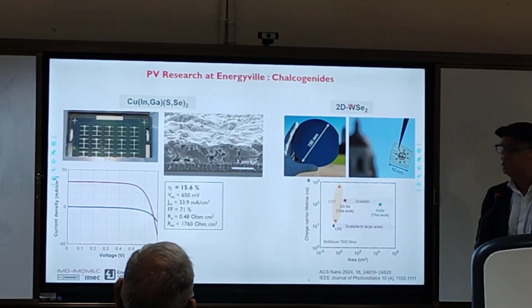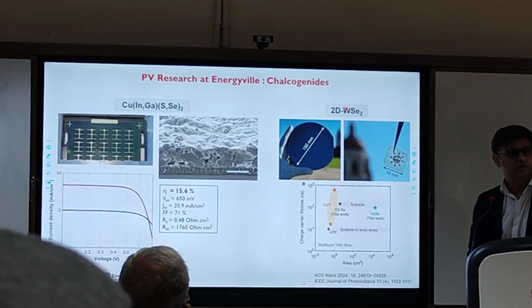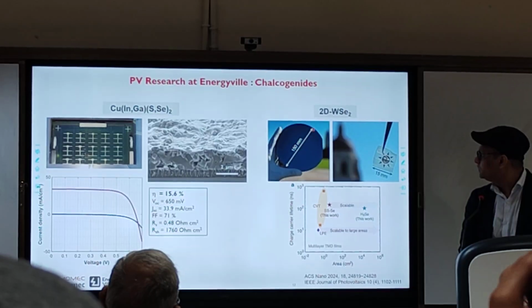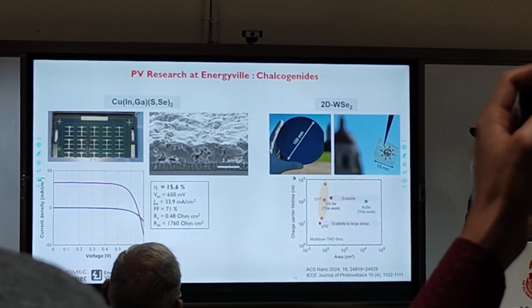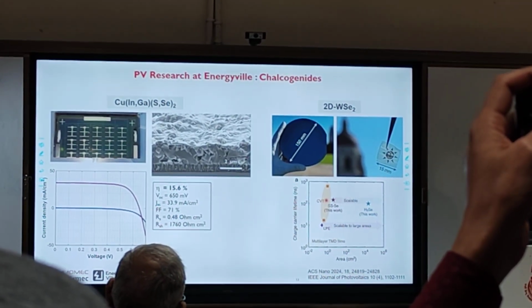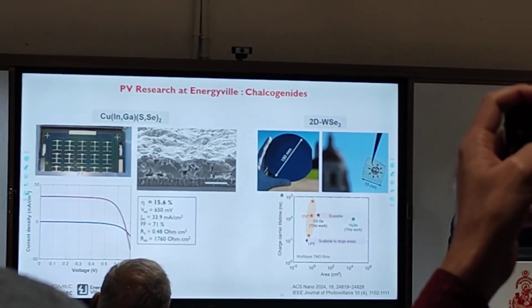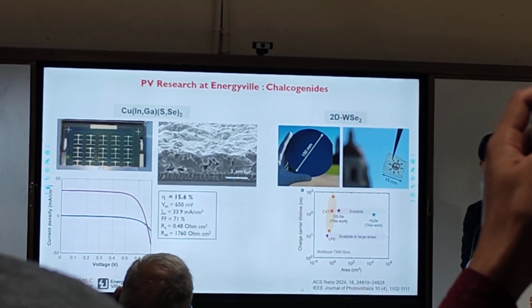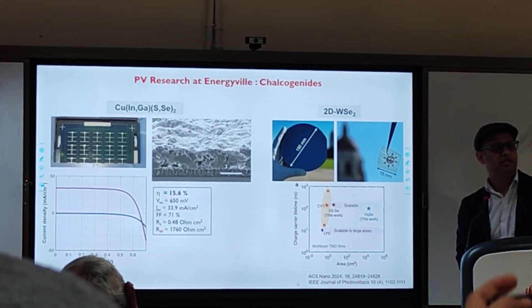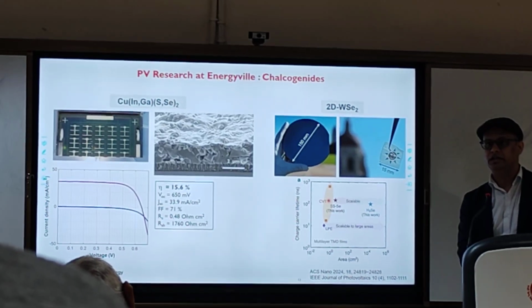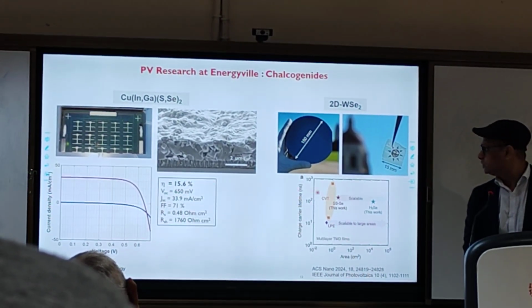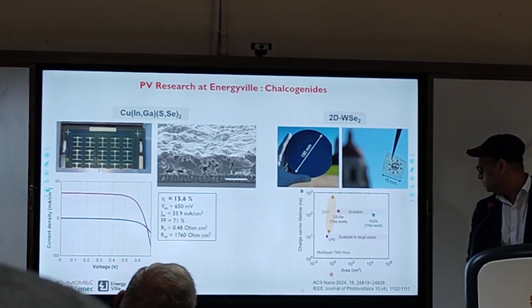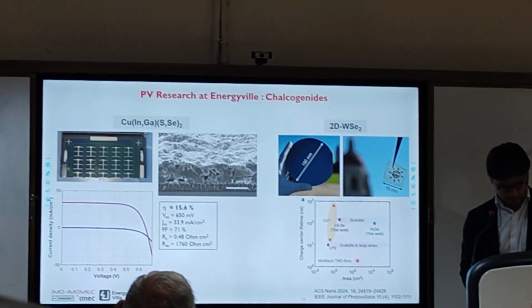We are also doing something recently in 2D materials. Tungsten diselenide can be grown on silicon at fairly large scale with very high lifetime. So this is quite an interesting result. Imagine a 2D layer which you can grow at fairly large scale, still maintaining the high lifetime. So the material quality still remains pretty good. This is something very recent. We published in fact this year itself.